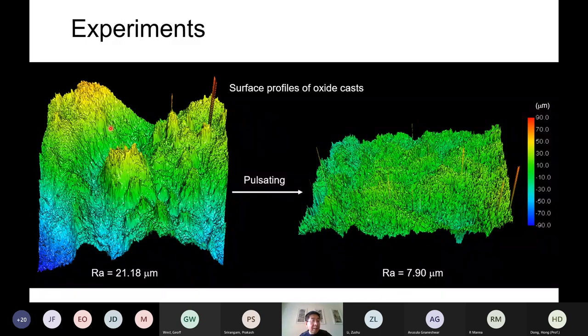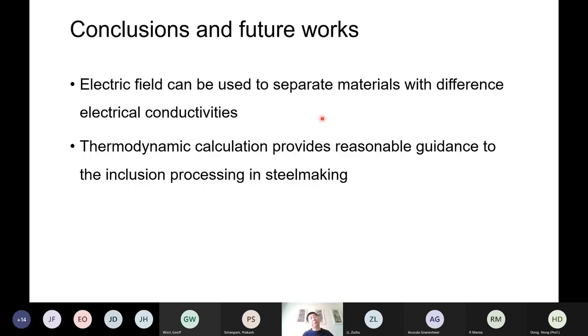This is slag without electropulsing. We did the solidification and used a 3D surface profiler to see the surface. This is an experimental result for the surface without electropulse. The R value is 21.18 micrometer. When we use the electric current, the surface became like this, and the R value according to measurement is reduced to 7.9. This one is now under review. So that is the story about our case.